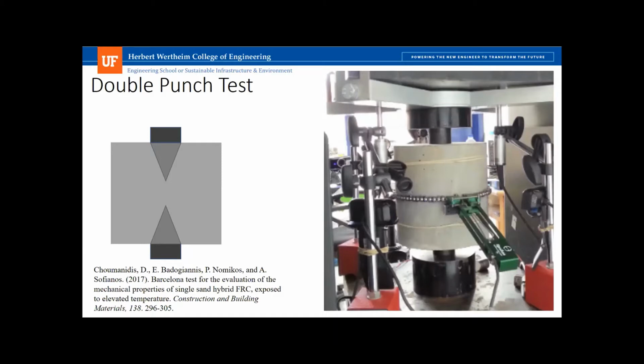There is an ASTM in works that's being used to develop this test. It's still very complicated. You still need a displacement controlled closed loop machine to do this. And the extensometer costs on the order of about $6,000, not to mention the data acquisition to record this. So it's still really out of the realm of capabilities for most precast plants and local testing labs to run. Plus, it's somewhat complicated to run comparatively because of the data acquisition and logging.